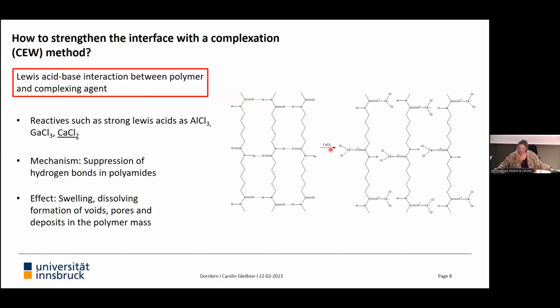So when I'm bringing my polymer in contact with the solvent, so with calcium chloride, ethanol, and water, the calcium chloride would form a complex with the oxygen atom of the amide group, because it has a higher electron acceptance capacity. And as you can see, these hydrogen bonds are suppressed. So as a result, there's a lack of these intermolecular bonds between the polymer chains, and these polyamide chains get loose.